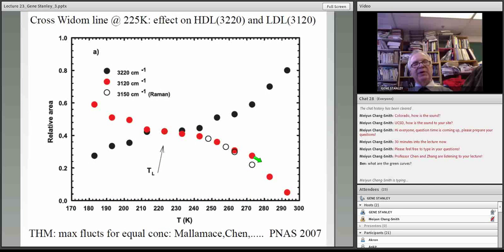Let's see what happens when we look at them. Here at very, very high temperatures, we see a very big amount of HDL and a very small amount of LDL. And as we cool, the amount of LDL increases and the amount of HDL decreases, and they cross right around this magic number of 225. And below that, the same trend continues in the other direction. So this is fairly striking because it's not based on some complicated subtlety, but it's based on area. Area is relatively insensitive to tiny mistakes, tiny inaccuracies.